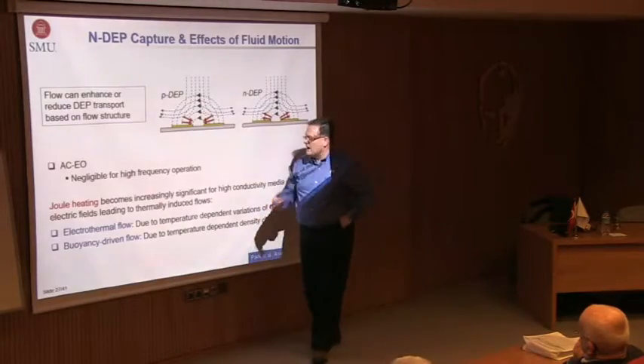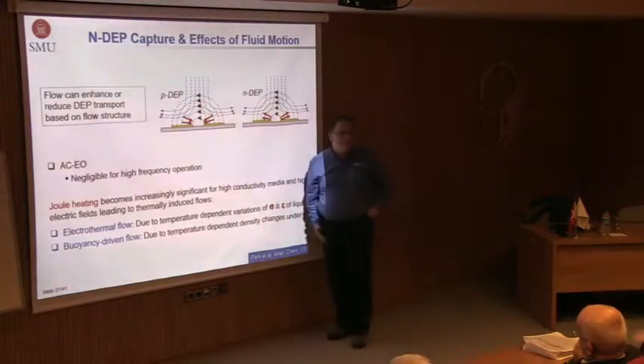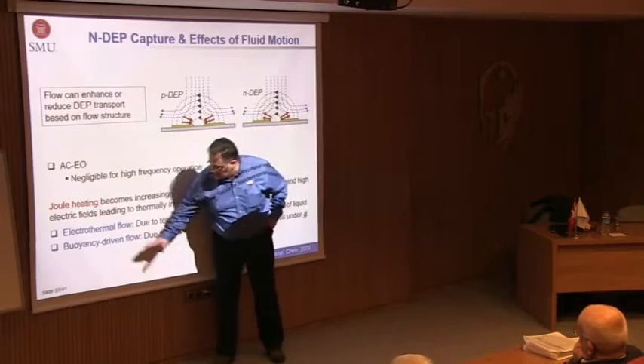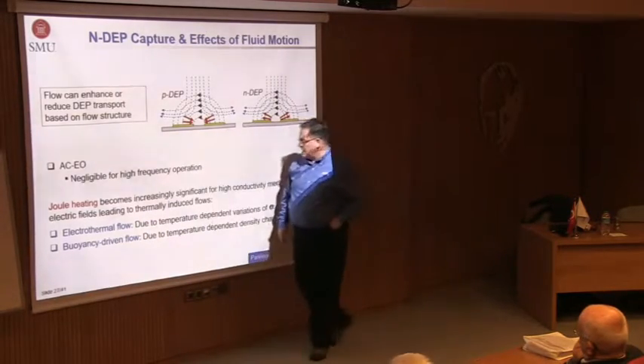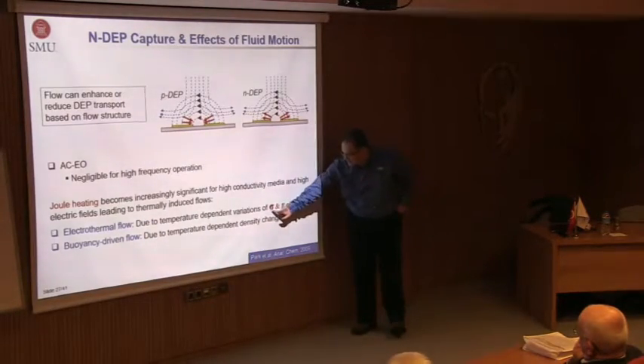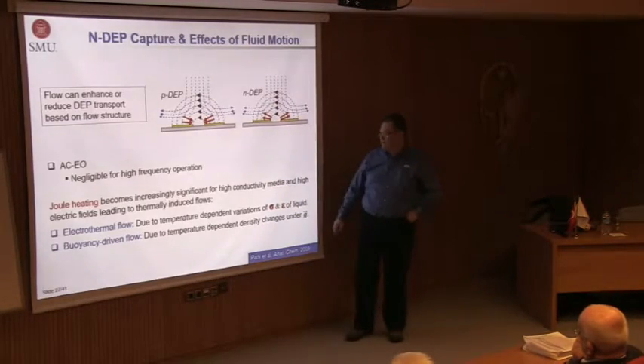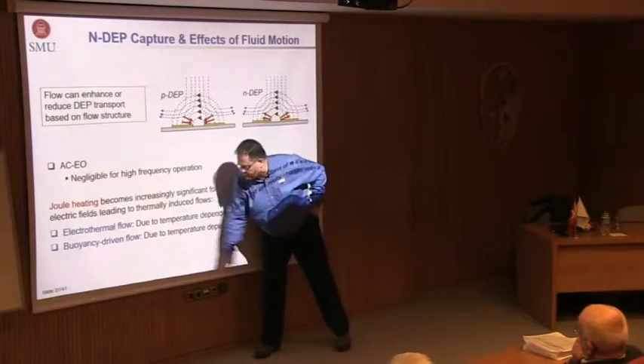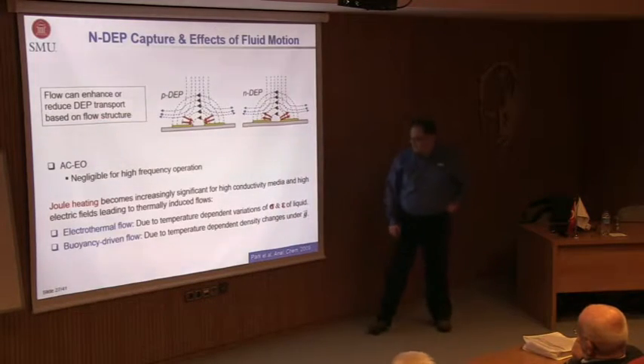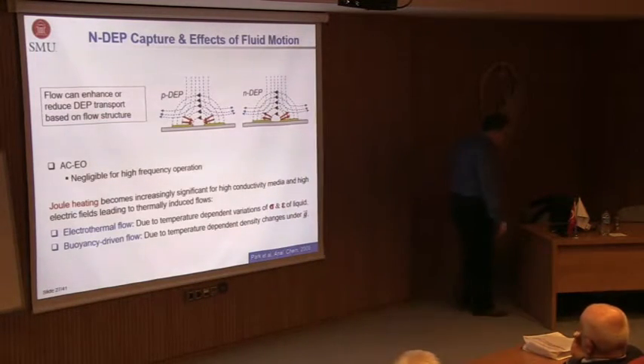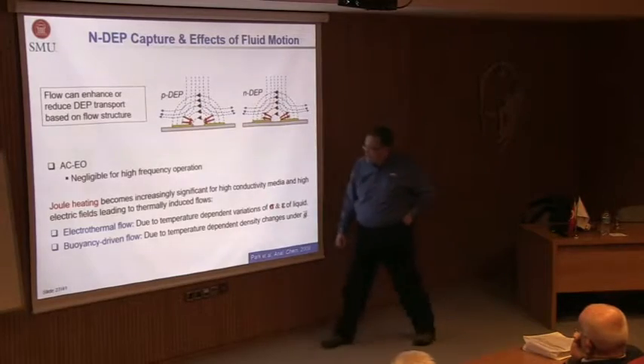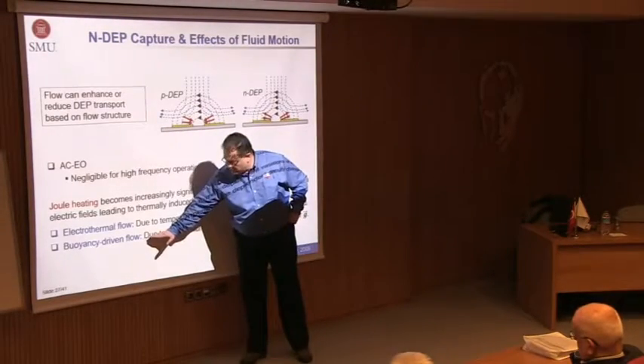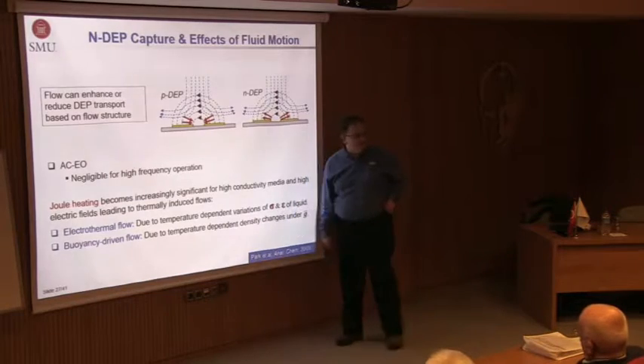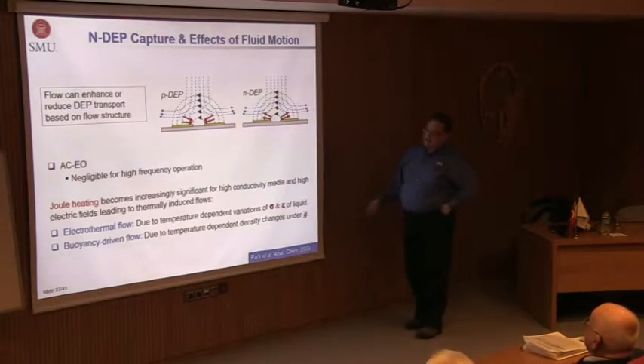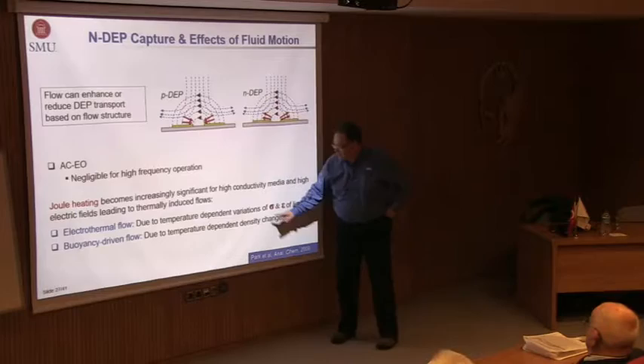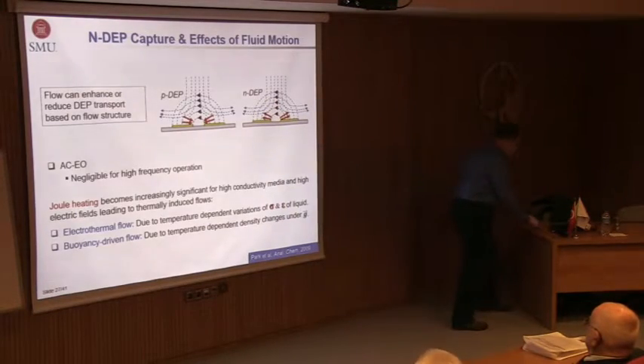Because we're using a high conductivity fluid, we have Joule heating in this system, and that means I can have electrothermal flow, which happens due to temperature-dependent variations of conductivity and permittivity of the liquid, or you can have buoyancy-driven flow that happens due to the density fluctuations under gravity. It turns out that buoyancy-driven flow is not, you know, critical for microfluidics. You know, there's a critical Rayleigh number, as you well know, and we don't get that high, but electrothermal effects can be utilized.